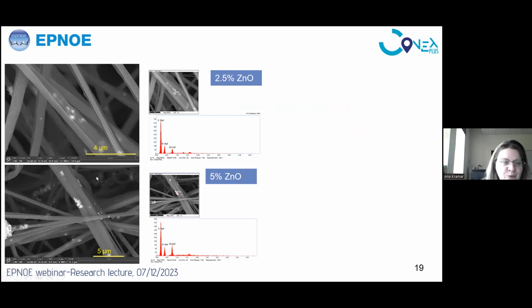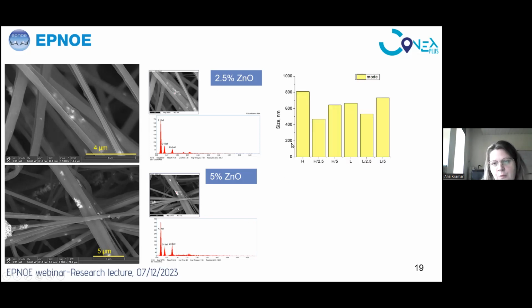And I would like to get your attention to see, for example, this main fiber in this lower picture. We can actually see the mechanism that we were speaking about earlier, that we have, in fact, two fibers that are coated with a thin layer of polyethylene oxide, and zinc oxide nanoparticles are actually inside this composite.